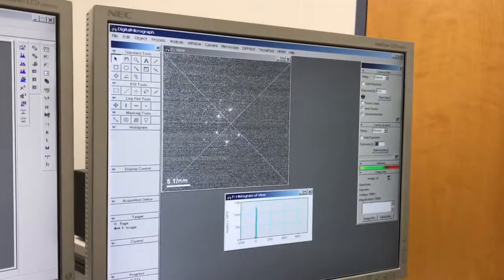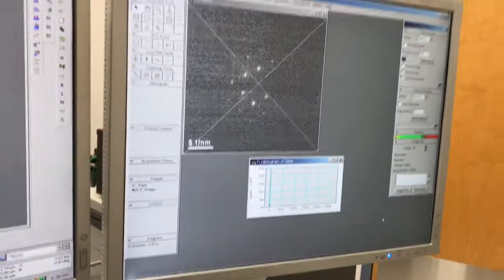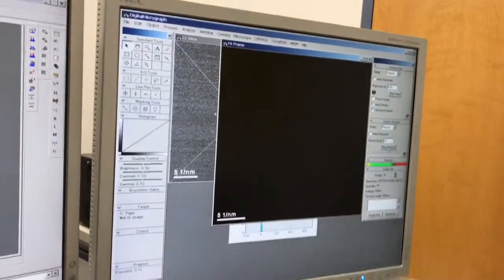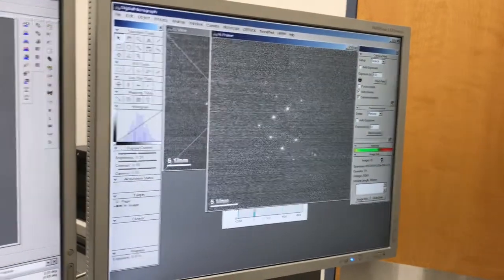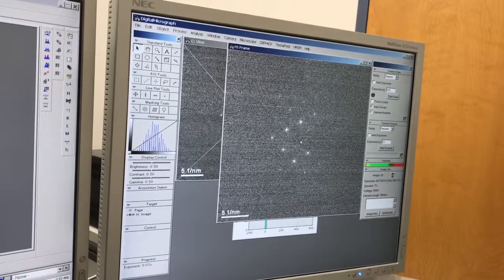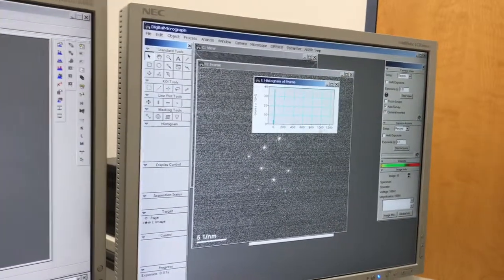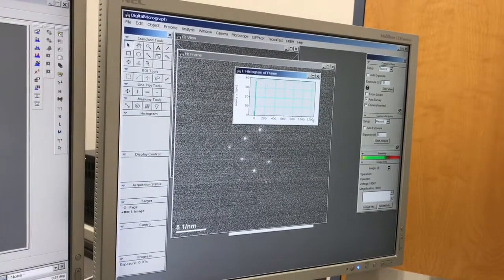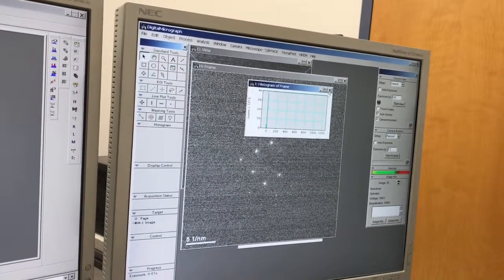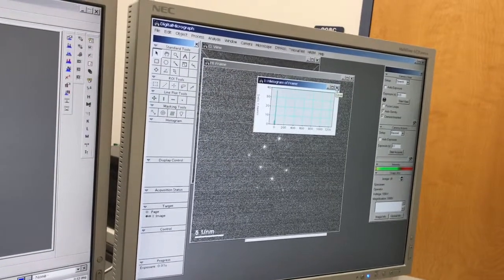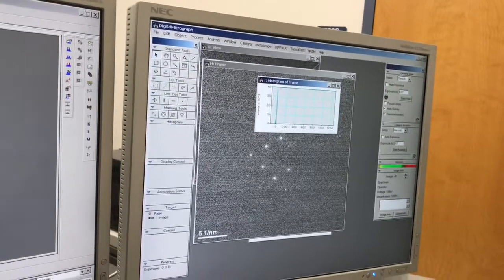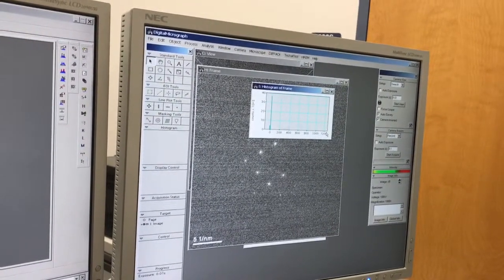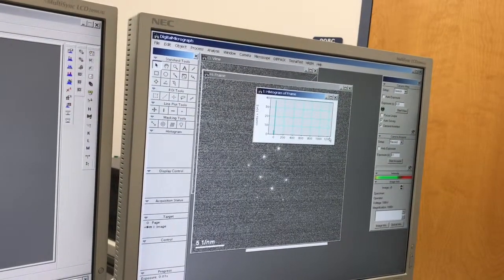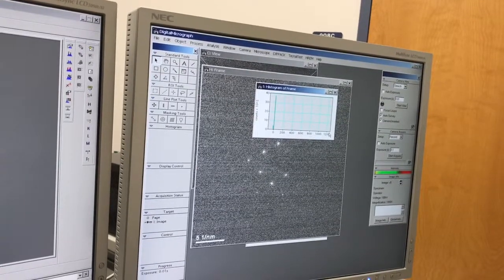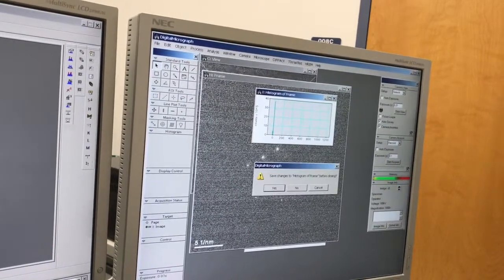So I'm going to do a test exposure here. We'll do 0.1 seconds, and we're going to see how this looks. You can see it's very noisy. I can see the spots, but if I do analysis histogram, I can see now my max counts is around 1,200. So again, the camera has good linearity. If I go to say 1 second, this should get me to around 12,000 max counts, which is still well below the max dynamic range. In fact, it's more like 20% of the dynamic range, and that will improve my signal to noise.